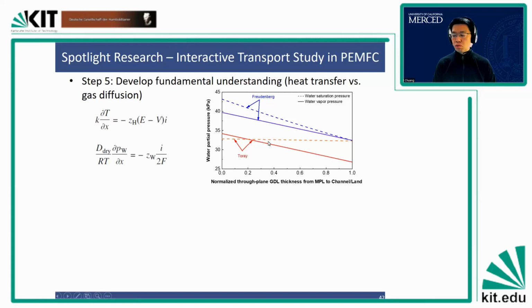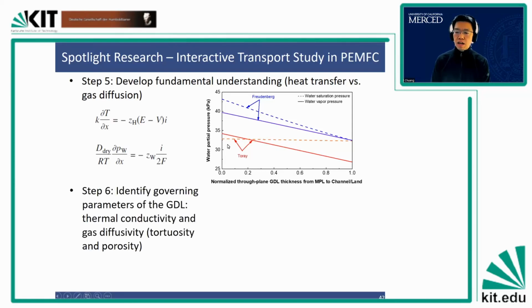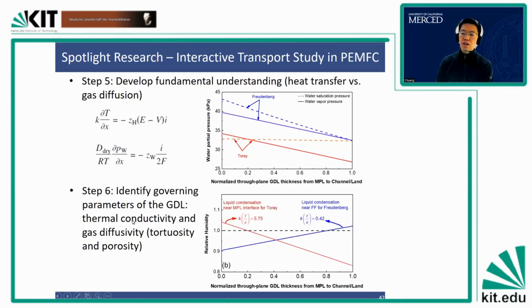But for the red, which is Toray, it's the opposite. You have the saturation pressure here on the dotted line, but the water pressure is the solid red line. And you can see when the water pressure is above the saturation pressure, you will start to condense, and it condenses very quickly near the catalyst layer side. And so once we develop this fundamental understanding, we identify governing properties of the gas diffusion layer. These are thermal conductivity and gas diffusivity. Thermal conductivity is K. Gas diffusivity can be represented as tortuosity divided by porosity, right?